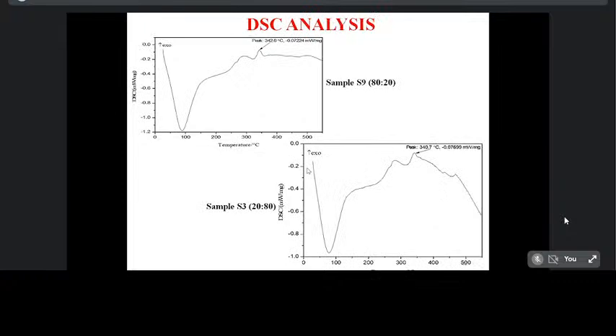So the next one is the differential scanning calorimetry analysis. Here we have the same sample S9, 80:20, and the sample S3, 20:80. The minimum peak value was achieved by the sample S3 at 340.7 degrees Celsius, and the maximum was achieved by the sample S9 at 342.6 degrees Celsius. The differential calorimetric analysis was done with the same TGA instrument, and it is used to find out the heating value of the produced biomass briquettes.